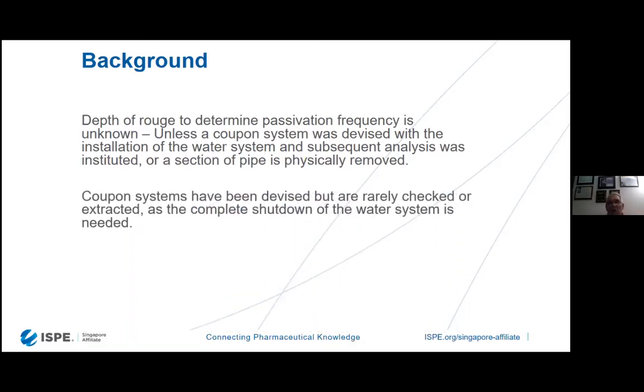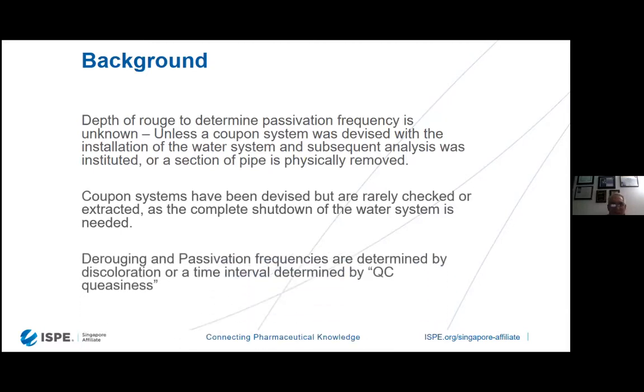And we decided to go to this kind of system, which I call QC queasiness. Lots of times, derouging passivation is determined by discoloration, or a time interval that someone decided by QC. So how did this happen? Typically QC would say, well, we're going to do derouging passivation once a year. And as a scientist, I would say, how did you arrive at that? They said, well, we do everything else once a year. It was not based upon scientific data. It was based upon what QC could tolerate before they couldn't tolerate it anymore.